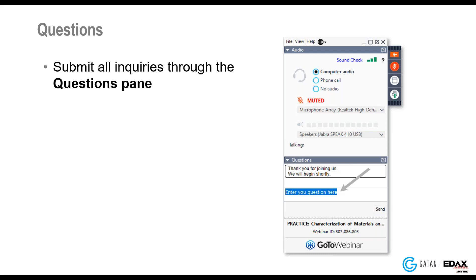Question: What is the minimum detection limit? Honestly we're still really discovering what that is. We've tried this on a number of different material systems with pretty good success. We've analyzed materials with a few weight percent lithium, and I think it's reasonable to expect we could go below that and push down towards one weight percent. Ultimately it's going to vary from material to material and may depend on whether a lithium-free analog is available to act as a standard, but somewhere approaching one weight percent is a realistic expectation at this point.